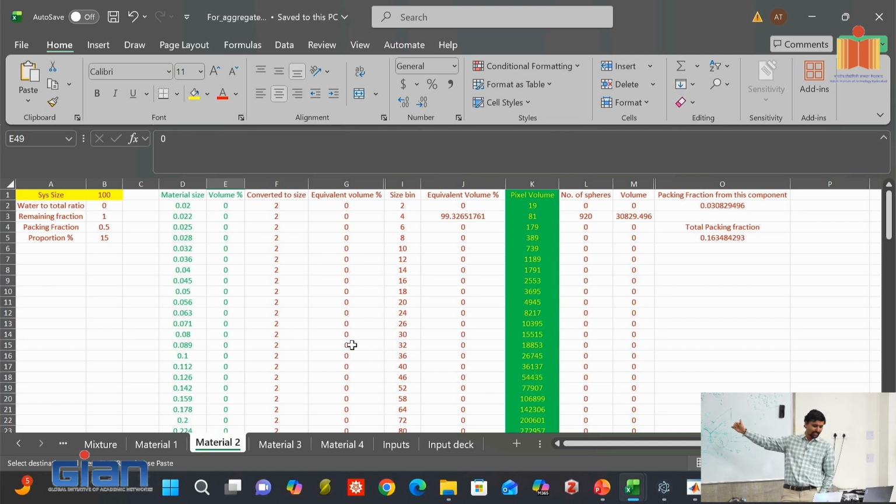For this, I think it ended up being, you see, for 2 micron it was 50. For 4 micron I had to go to 40. For 8 and 16 I had to go to 35%. I had to have the remaining as pores, because the random seeding did not allow me to put more. I already put a 16 micron diameter particle, right? Instead, when you put 2, chances of putting a 2 are very high.